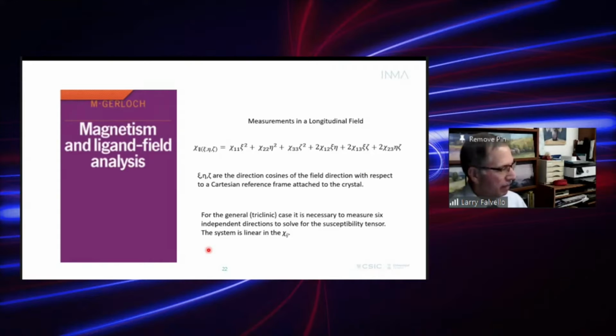But Magnetism and Ligand Field Analysis by Gerloch gives details about how you would measure a single crystal magnetic susceptibility tensor, both when you have a longitudinal magnetic field, that is, when the reference direction you've oriented the crystal along is parallel to the field, or perpendicular, as it might be in a Faraday balance.